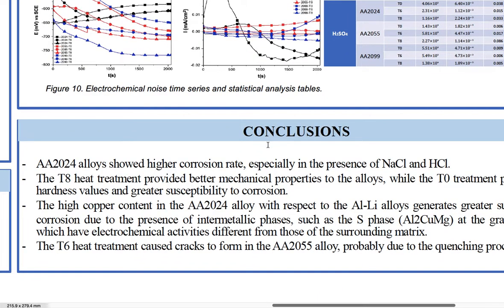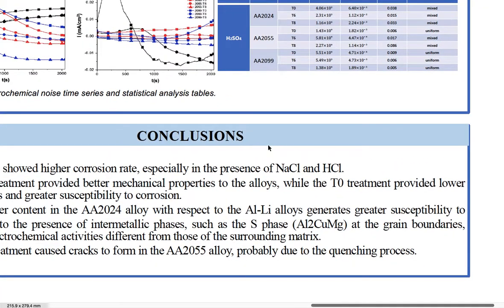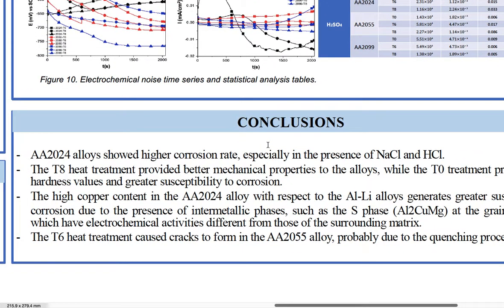Conclusions. 2024 alloys showed higher corrosion rate, especially in the presence of sodium chloride and hydrochloric acid. The T8 treatment provides better mechanical properties to the alloys, while the T0 treatment provides lower hardness values and greater susceptibility to corrosion.